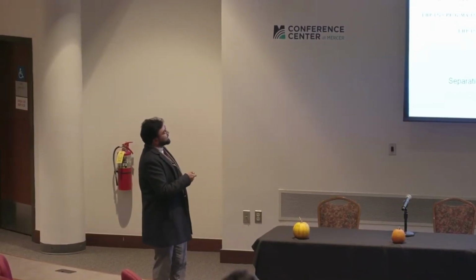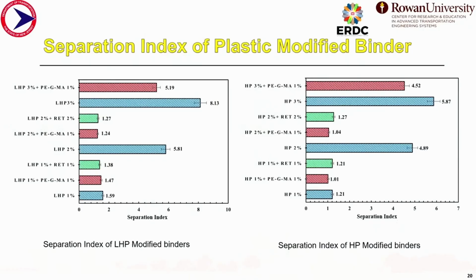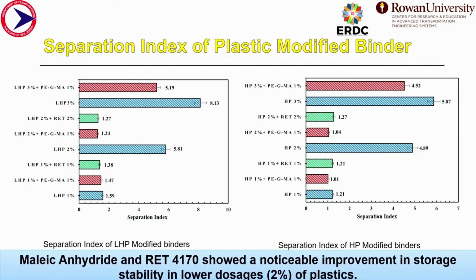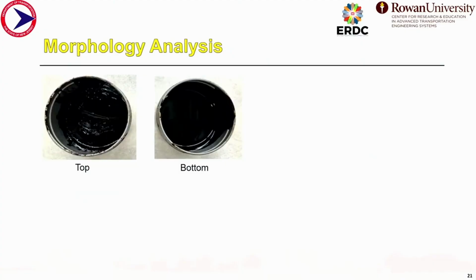However, when we add the maleic anhydride and the RET stabilizer, we can see there is an improvement for both LHP and HP plastic in terms of phase separation. That means both the maleic anhydride and RET are showing noticeable improvement in storage stability, at least in terms of 2% of plastic. To better investigate this separation index, we did fluorescence microscopy at both the top and bottom sample to see the polymer distribution in the blended mixture.